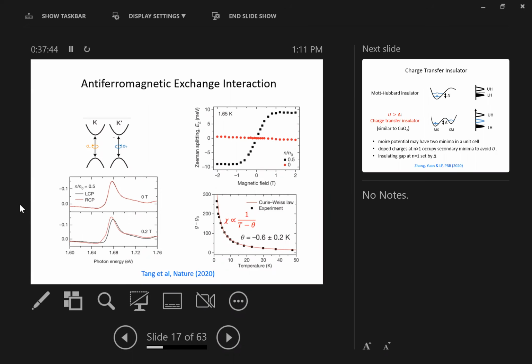So one can probe the amount of spin polarization by applying an external magnetic field and using circularly polarized light. If there's a valley polarization, the left and right polarized light will couple differently. So it leads to so-called magnetic circular dichroism. The optical response is different depending on the polarization. And so if you now look at the asymmetry in the response between left and right circularly polarized light, it gives you a measure of the Zeeman splitting of the excitons.